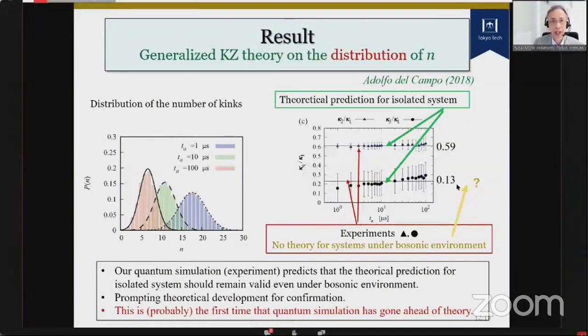And we tested this prediction with the D-Wave data. And we found, very surprisingly, that those data points lie on the theoretical prediction within the error bars. But we learned from the previous page, on the average number of kinks, that the D-Wave qubits on the D-Wave chip are clearly under the influence of a bosonic environment. But the experiment on the distribution shows that the experimental finding agrees with the theoretical prediction for the isolated system.